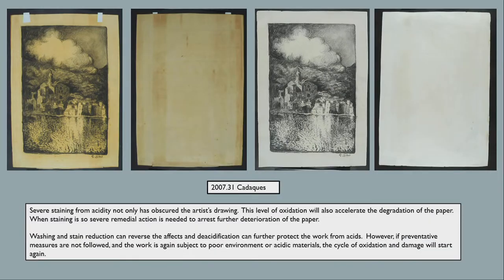Another example from the Dalí collection, this is of Cadaqués. Severe staining from acidity not only has obscured the artist's drawing, but the level of oxidation has also accelerated the degradation of the paper. When the staining is so severe, remedial action is needed to further prevent deterioration. Washing and stain reduction, in this case, using other solvents, can reverse the effects, and then neutralizing it or deacidifying it, giving it basically like Tums or Milk of Magnesia, a treatment so that the reaction with the atmosphere can be slower. This can further protect the work from acids.